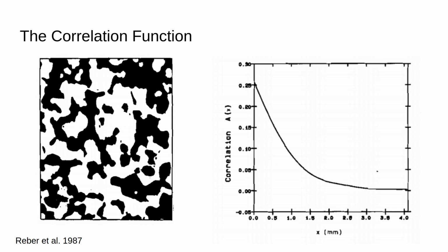If you drew a lot of lines and did this a lot of times, you end up with a pretty smooth function that describes the way the snow microstructure decorrelates as you shift it more and more. To squeeze just one number out of this correlation function, we look at how far you have to shift before the correlation drops below 1 over e of its original value. That's, to a large degree, an arbitrary threshold. I've illustrated it on the right. For this, it's 1 millimeter.